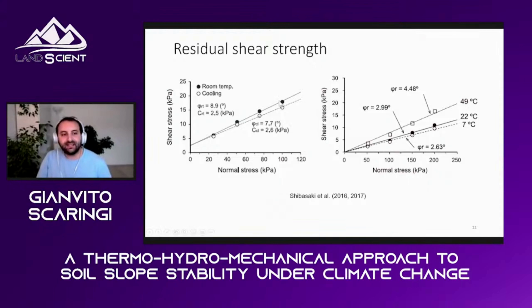But then they cooled down all the experiment. Normally, you cool down the water bath that is saturating and the circulating bath that surrounds the samples, and in this way you cool down also the sample that is inside. They cooled it down to +7 degrees Celsius. They did not freeze the soil. They just cooled it down to simulate autumn conditions, for example, in the slopes of this area in Japan.